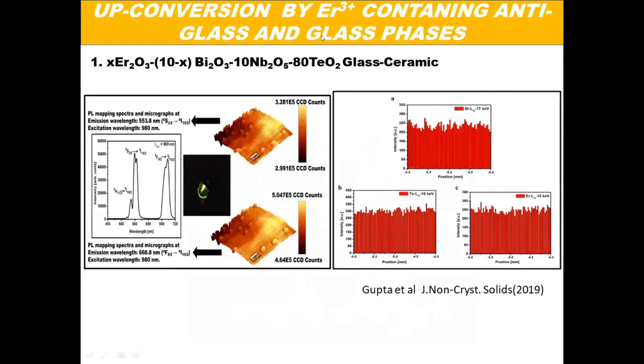So we functionalize these materials with erbium oxide. You add some small amount of erbium oxide in bismuth niobium tellurite, and you get a glass ceramic. It's a glass ceramic because it has both the glassy phase and the anti-glass phase coexisting. And we excite it with IR light, 980 nanometer, which is generated by a diode laser. 980 nanometer lies in the near infrared region. And you can see this picture. The sample was actually yellow in color, but here the color of the sample is green. You can see this photograph where I am pointing the arrow.